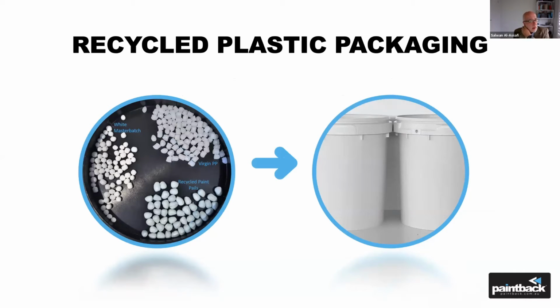So we end up with resin beads, recycled resin beads, and then we add it to virgin. So we don't use 100%. We've gone through a testing process. We determined that a safe percentage of recycled content would be around 30%, to be on the conservative side. So we have this 30% of recycled polypropylene. We add it to virgin material, and then we add, in some cases, white masterbatch to give it the white color, or, depending on the client, perhaps we leave it without any color.